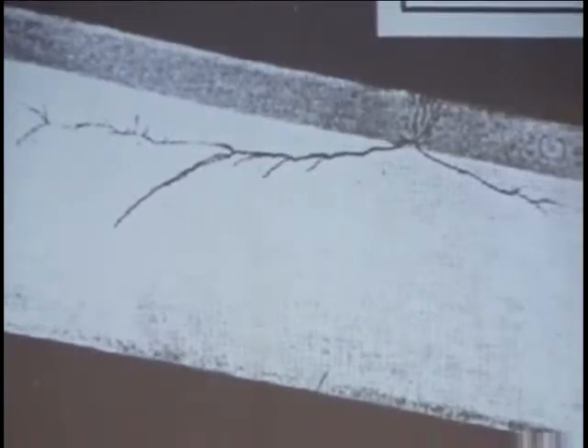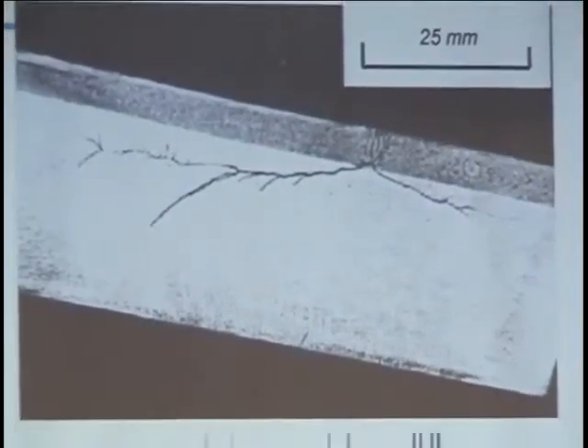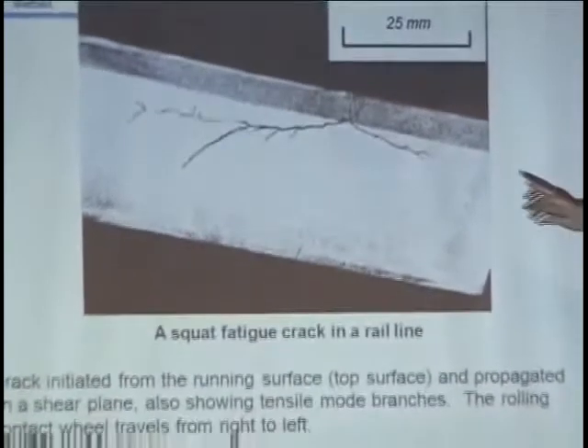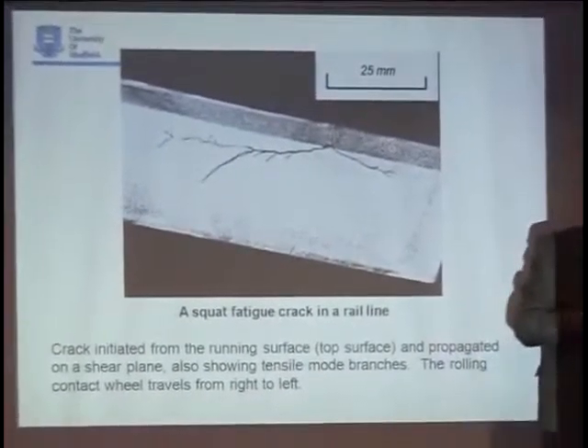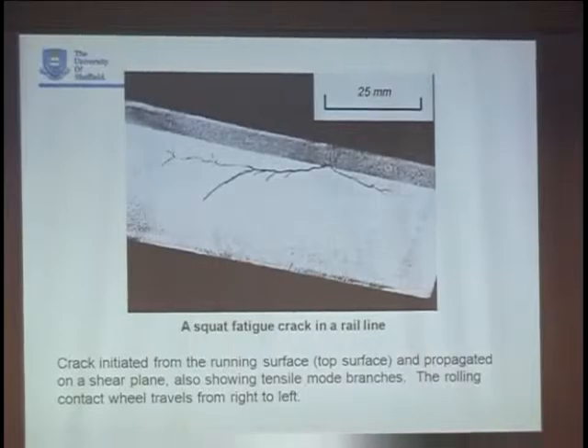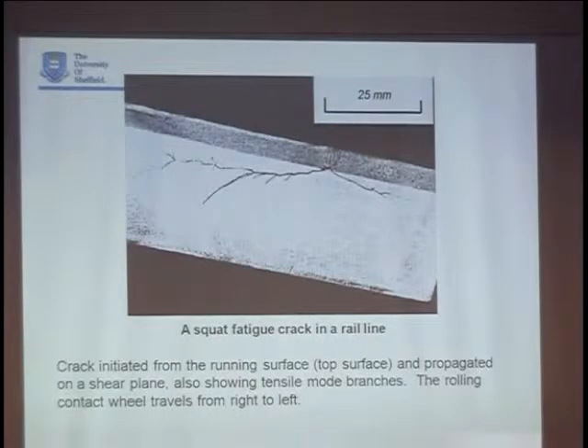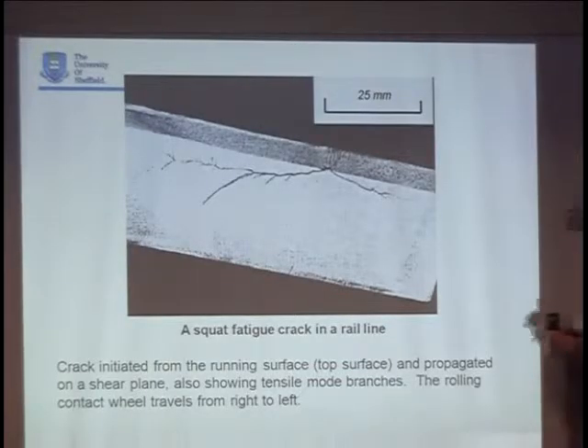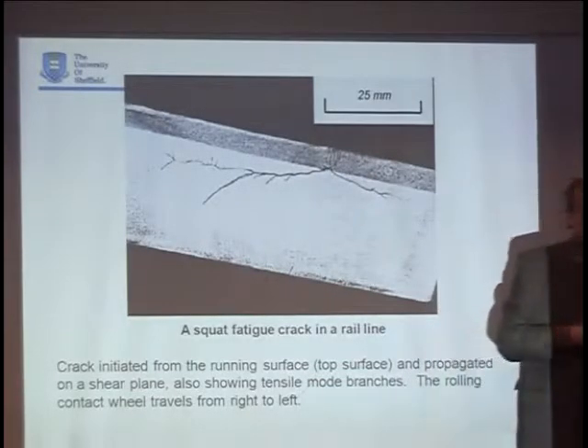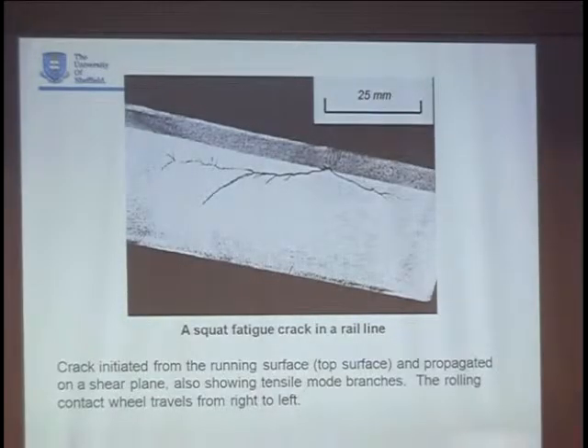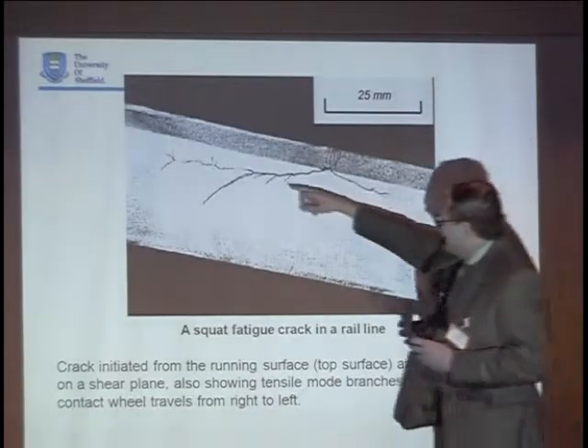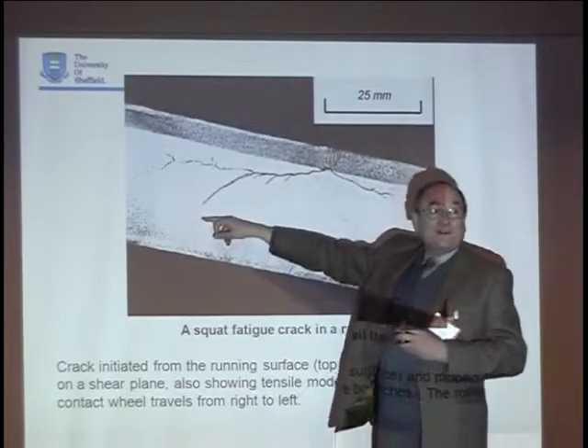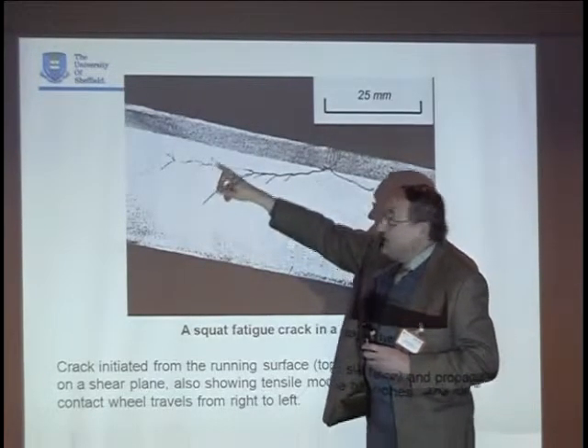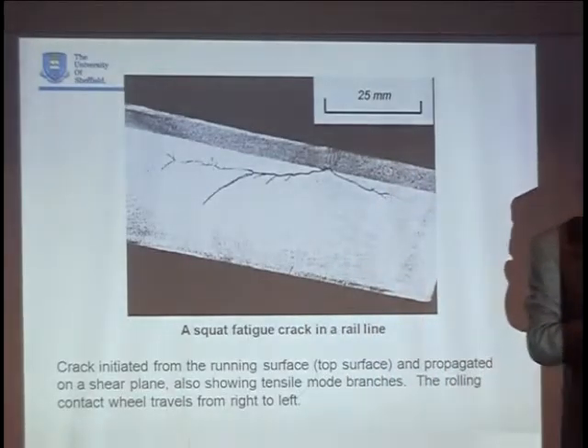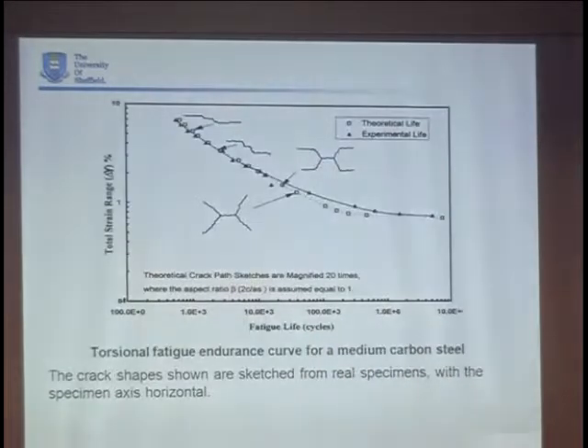That turns out to be a plane that's under high shear stress, cyclic shear, so it's a shear mode crack. And if you live in a country with high-speed trains and a temperate climate, where it rains, so you get a bit of fluid around, then those cracks grow quite happily. No point in trying to grow them in Arizona, because it's too dry, there's no fluid, and instead you get cracks going across the line, like this one, which then lead to a fracture. This, and the branches upwards, will be the Mode 1 type of crack.